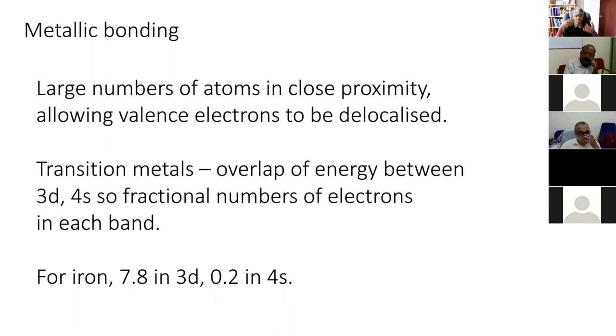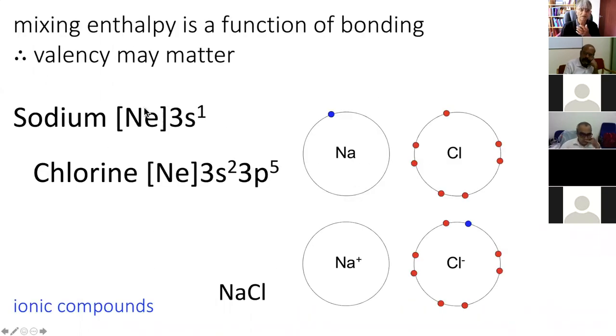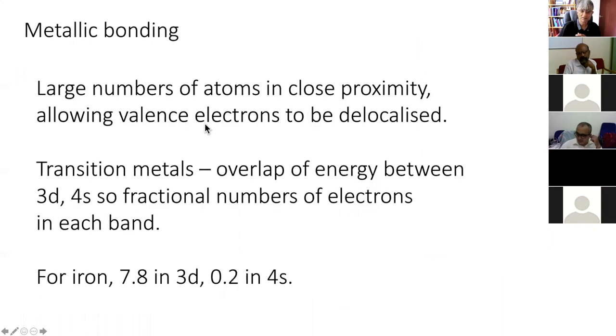And when we talk about transition metals, it gets even a bit more complicated than that, because if I go back to the previous slide, these shells here have a lower energy than this one. The electrons in these shells have a lower energy than this one. But in the case of the transition metals, there is actually an overlap of energy between, for example, the 3d and 4s bands. So even though 4s should be a higher energy level than the 3d in your ionic compound, it's not the case for metallic elements. So you can imagine that the electrons spend a fraction of their time in the 3d bands and a fraction of their time in the 4s bands. So the total number of valency electrons for iron atoms is 8.